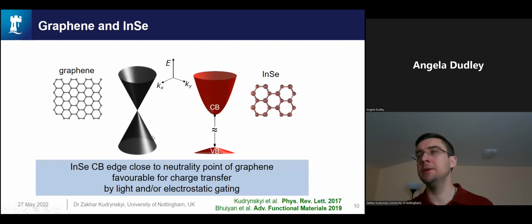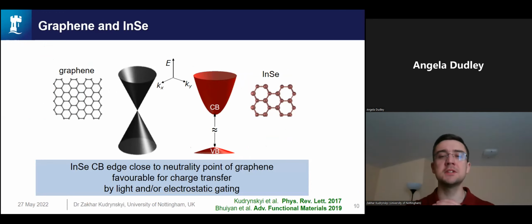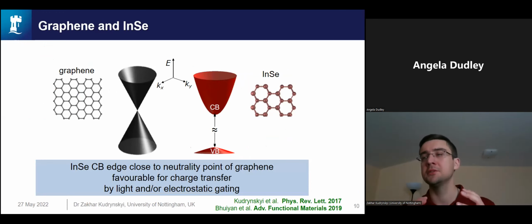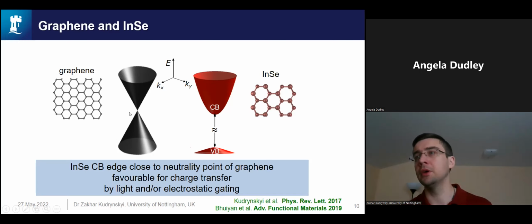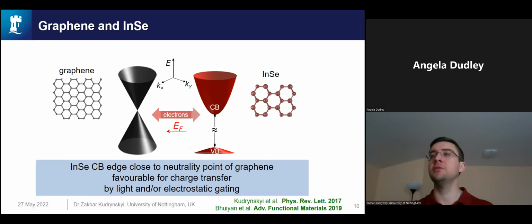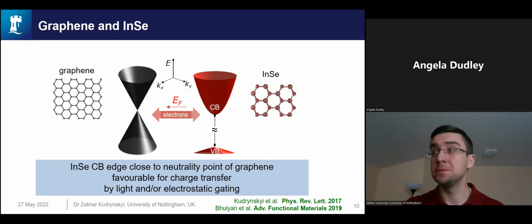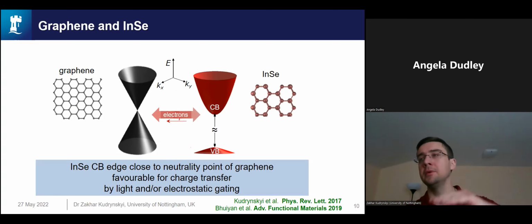And one of the interesting combinations of materials is also indium selenide and graphene. So why indium selenide and graphene? What is so special about these two materials together? Well, it has an interesting band alignment for a range of layer thicknesses. The conduction band edge of indium selenide is close to the neutral point of the Dirac cone of graphene. And this means that we can explore the charge transfer between graphene and indium selenide by different methods: by electrostatic gating, by moving the Fermi level up and down, and also by light illumination.